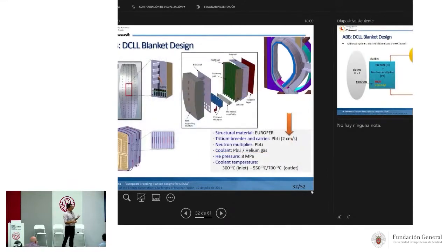But why dual coolant? Because we use an additional coolant for cooling the first wall. The first wall is one of the most important components of the blanket, the first component that the neutrons and the plasma radiation see. So in the end it is the component that receives the most important thermal loads, the most important radiation, and so on. So it's a quite important component. And for that reason, we use an additional coolant, which is helium, to cool this first wall. And for that reason it is the dual coolant lithium lead.